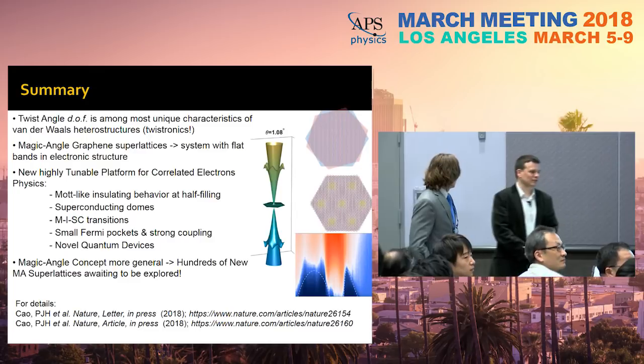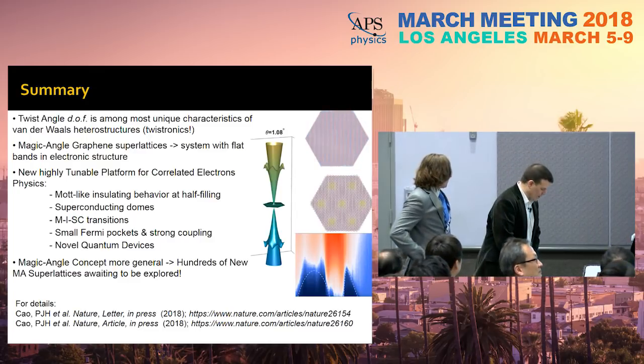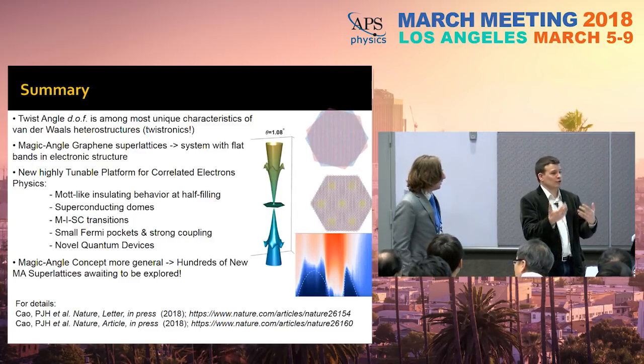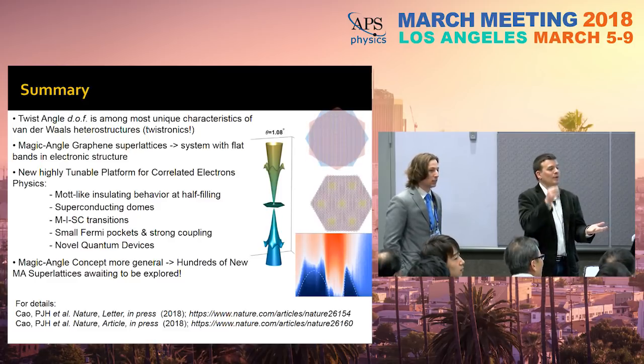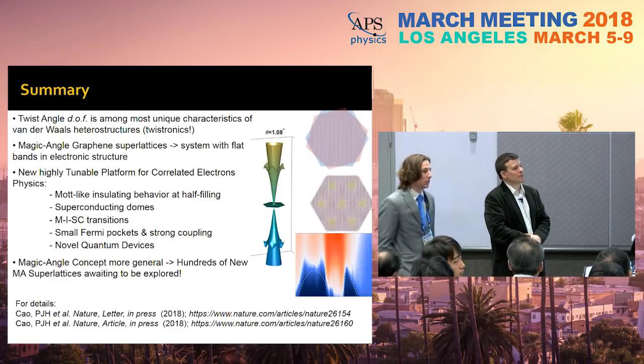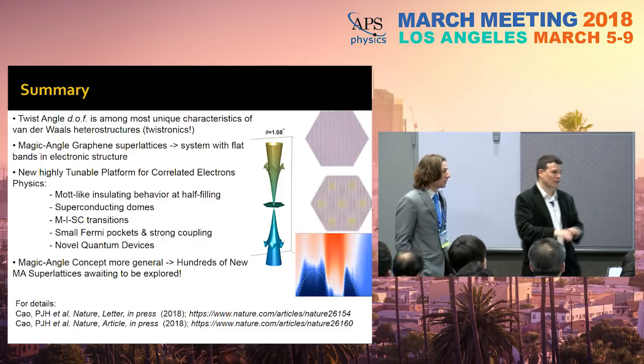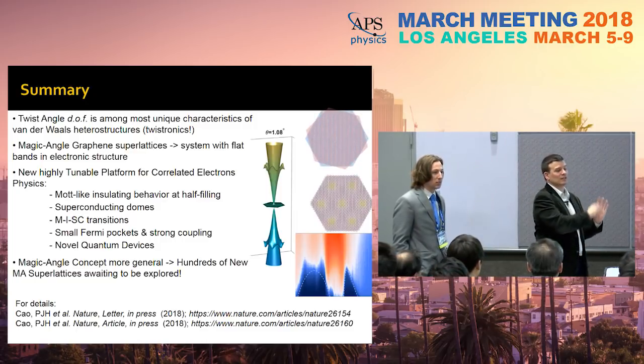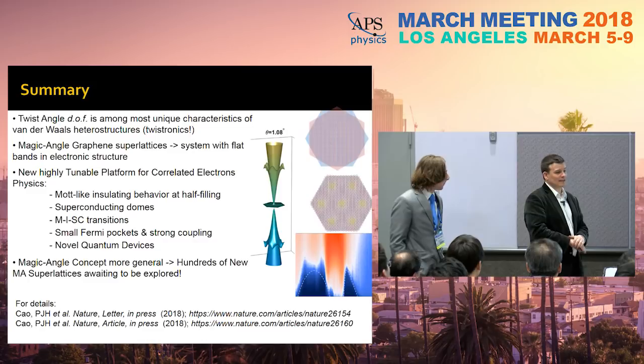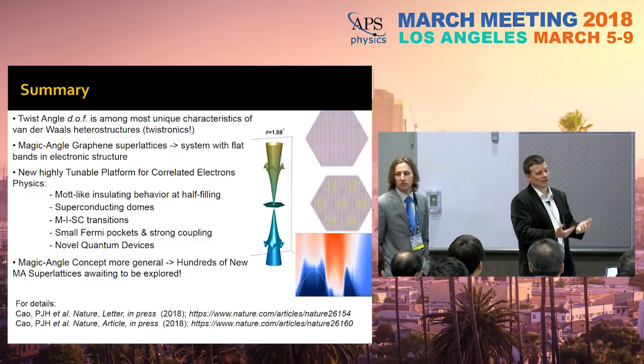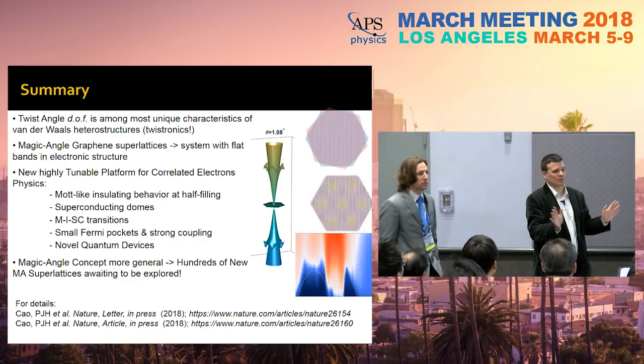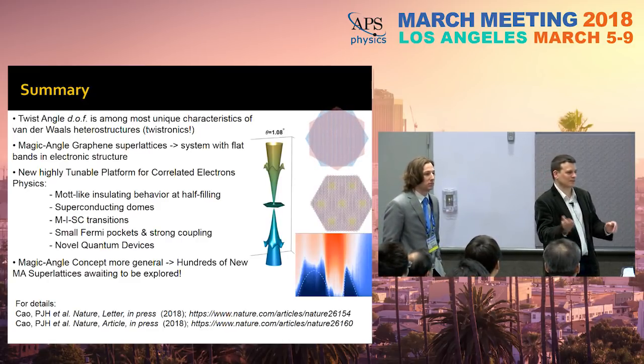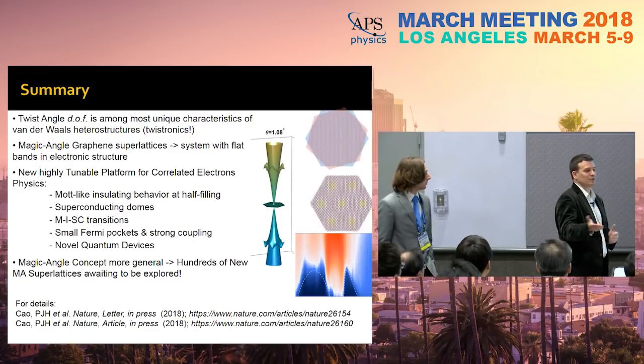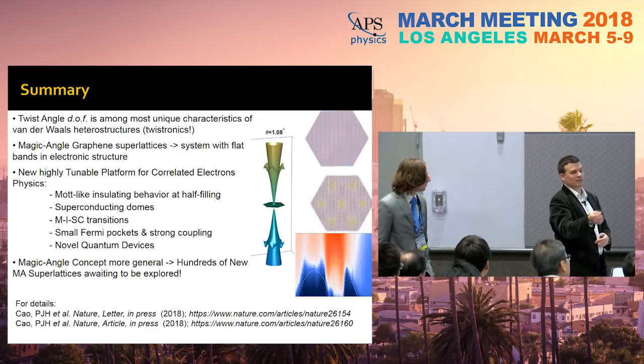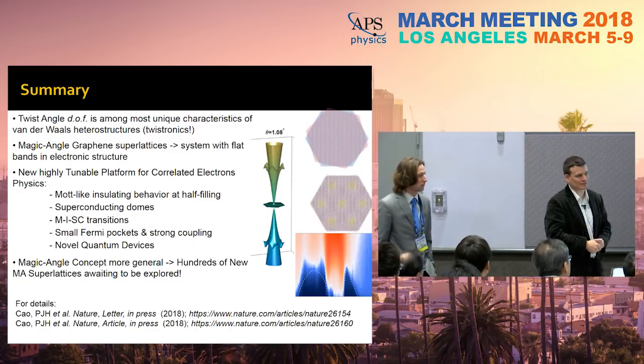Okay, that's an excellent question. We're not sure, because we do not introduce chemical impurities. We're always doping with gate voltage, okay? But some people have told us that some of the fluctuations that we see in the superconductivity, when you look at the details, seem to indicate that we are relatively sensitive, which is something expected when you have a non-S wave order parameter. But we don't have evidence to claim that, we're not doing a systematic study adding impurities. That's part of the beauty of this. We don't have to add impurities. We just add plain charge density.